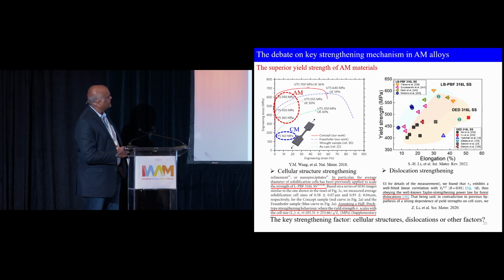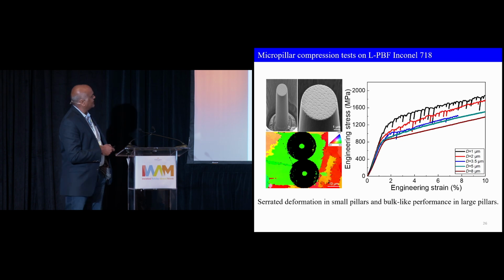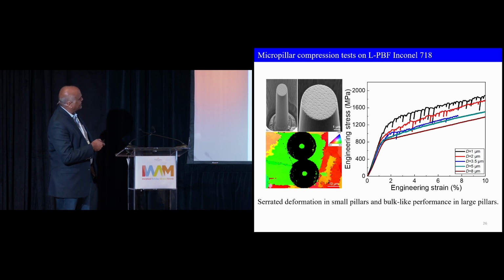So what we did to resolve this is basically go and do this micropillar compression experiment. So we take a focused ion beam, do milling, and we mill out these pillars. You can see the cell structures, and then we compress them.